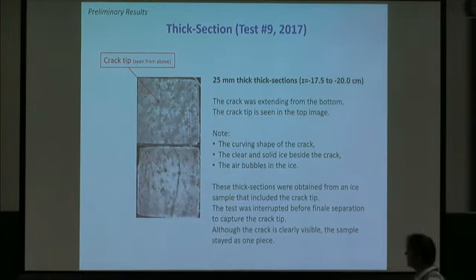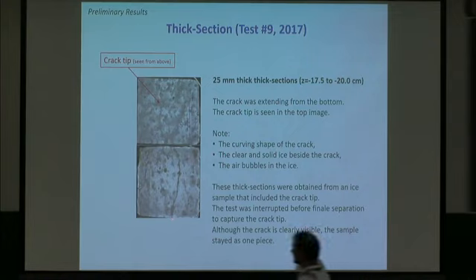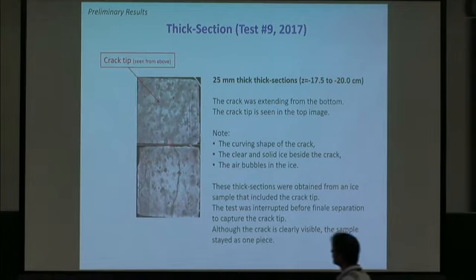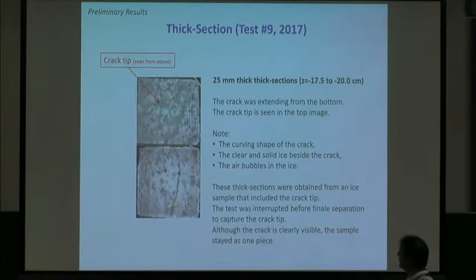What is captured in this photo here? We see the crack is coming, running here from the bottom. The bottom means, sorry, from the bottom of the photo. It's running like this, and the test was stopped in such a way that we have captured the crack tip, as you can see here. And you can also clearly see some of the porosity here in the ice, the brine pockets and so on. So what I can see here is that the ice is fully in contact on the sides here.